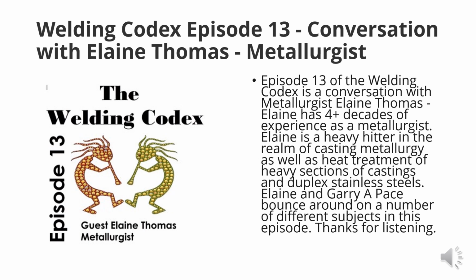I always required the duplex castings to have a second heat treatment. The second heat treatment helps the yield strength increase. It usually was a post-weld heat treat type of situation. Again, you take it up to about 2075 Fahrenheit, and then a couple hours before you take it out of the oven, you lower the temperature down to around 1925 Fahrenheit so that you're quenching from a lower temperature. You let that 1925 stabilize, and then you throw it in the drink and quench the liver and lights out of it, and you can get a higher yield strength by doing that. This is actually in the ASTM specifications for heat treating. It tells you to do this and gives you minimum temperatures at which to do it.